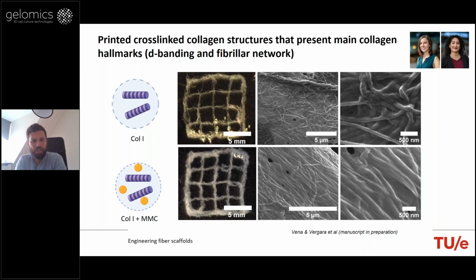What we are doing now is to further investigate if these constructs are cross-linked or not, because the reason for which collagen in our body does not dissolve is because it is cross-linked, right? Otherwise, it would just dissolve. So we are investigating in which form is the collagen that we are printing. And then we are using these collagen scaffolds to template processes like mineralization in order to generate and produce a piece of synthetic bone. And we believe that achieving this collagen density that presents the main hallmarks of the native collagen is crucial not just to the regenerative process, but also to the mechanical function of the collagen, and also to template processes like mineralization.